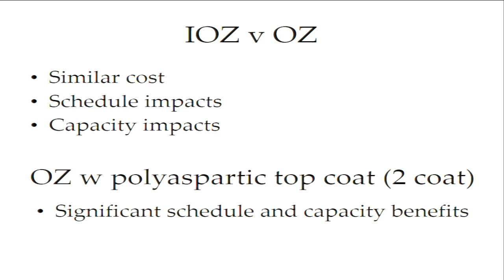It's important to go into a little more detail about inorganic versus organic. As Jeff mentioned, curing time can be an issue on inorganic zinc. Inorganic has to have moisture to cure, so you need to have a humid environment. You have to check on the cure. There's testing you do to make sure that you have cure when you're doing inorganic.